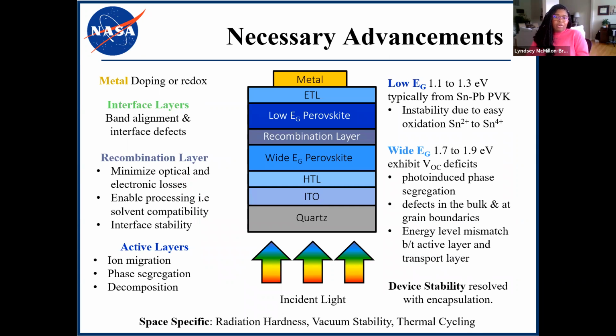And there exists great promise for these tandems, but there are also a lot of opportunities and necessary advancements that need to occur. So I'd like to focus on some of those advancements here, and they include understanding and mitigating the tendency for these metal contacts to dope the perovskite or undergo redox. And also interface layers need to ideally be defect free and compatible with the process methods of the rest of the device. So really I'm thinking of solvent compatibility here, which is quite a challenge when you're making these cells. And we also need to have the appropriate band alignment. Similarly, our recombination layers need to have low optical and electronic losses, and they need to exhibit solvent compatibility to processing techniques and be stable.